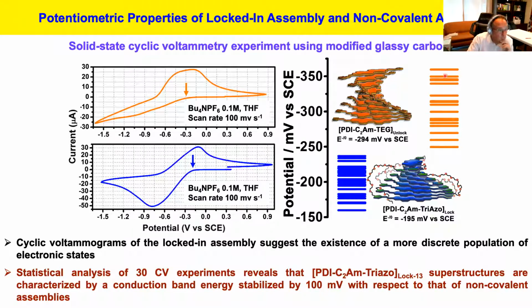And so the first conclusion that we can make here is that you can see that the energy, well, I guess the potential at which it takes to inject one electron into these non-covalent assemblies is spread over a wider electrochemical window for the parent assemblies when compared to the locked-in superstructure. But more importantly, when you lock this superstructure together, you are stabilizing by more than 100 millivolts the conduction band energy of these entities.